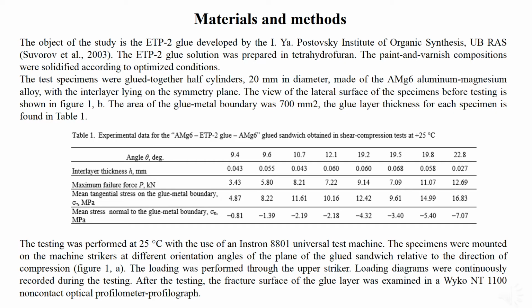The specimens were mounted on the machine strikers at different orientation angles of the plane of the glue sandwich relative to the direction of compression. As is known, at an angle of 0 degrees, the destruction of the glue sandwich occurs by cleavage. Therefore, in order to reveal the mechanism of shear-induced adhesive failure under the effect of normal compressive stress, the testing was performed at angles greater than 9 degrees.